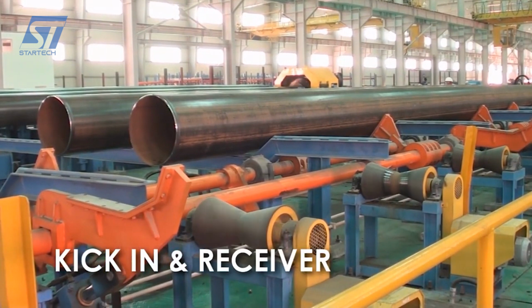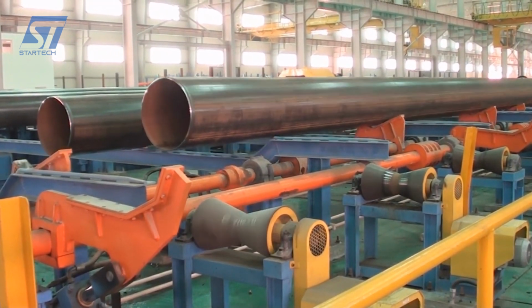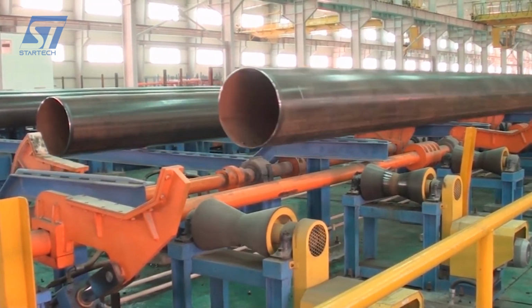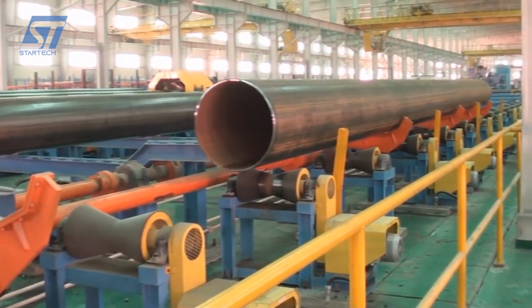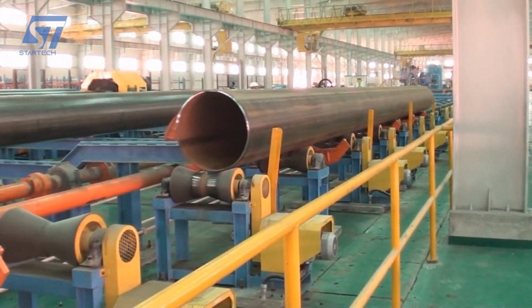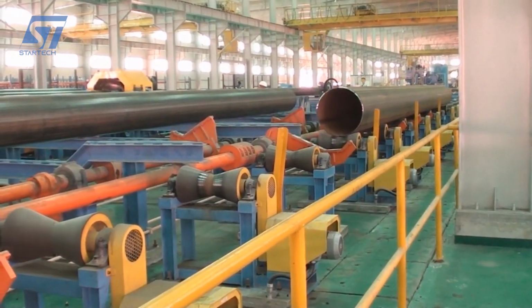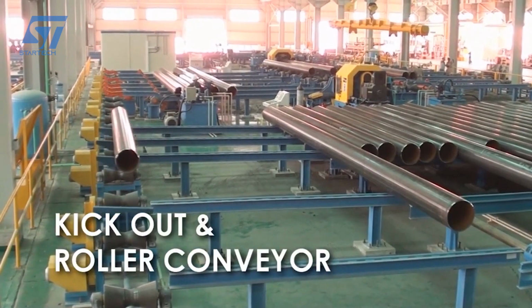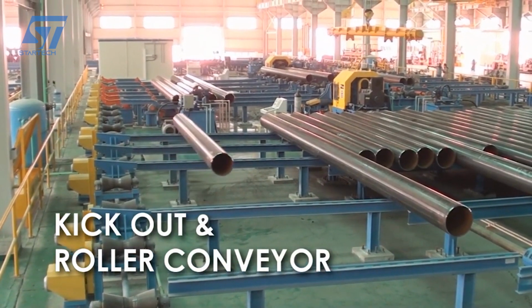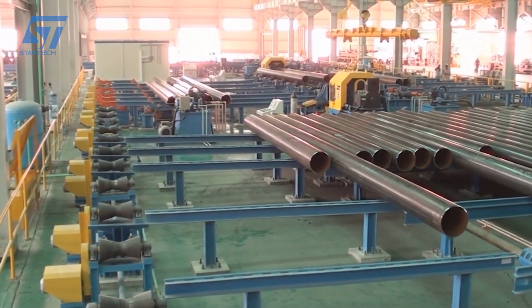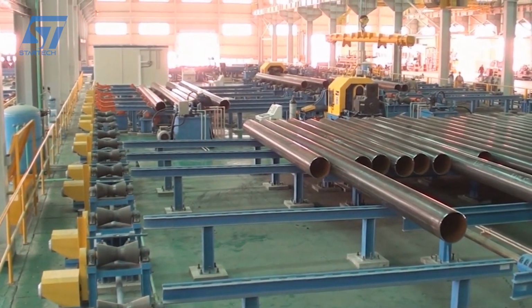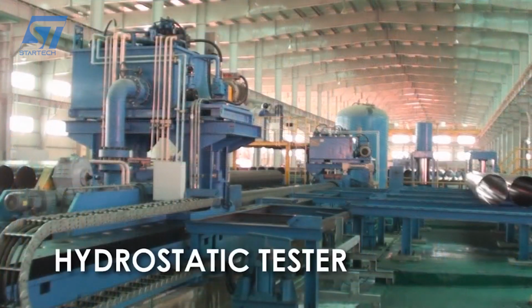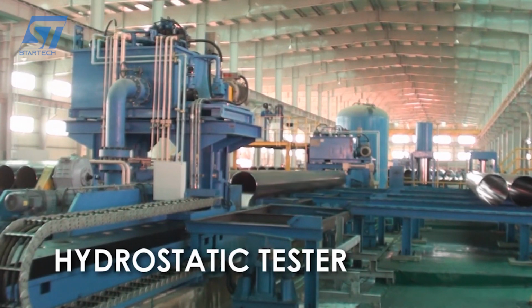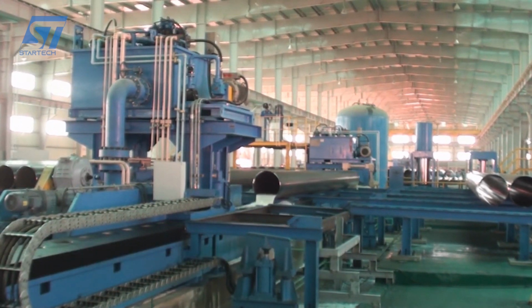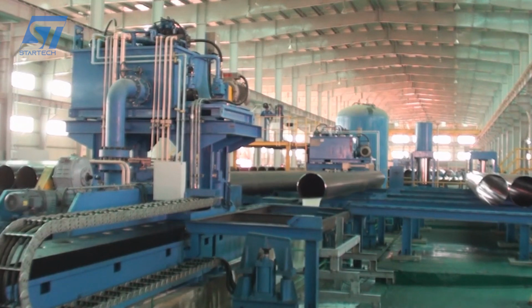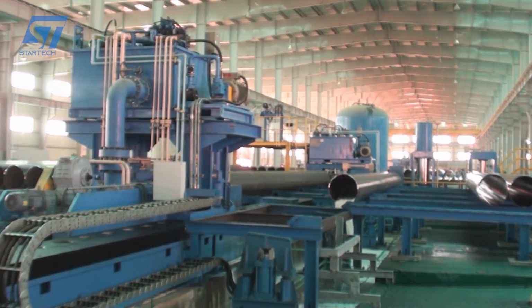The scrap rate decreased from 5% to only 1%, thanks to the ability to strictly control each stage, from forming to welding and cooling. The system allows quick conversion between different pipe configurations within just 15 minutes. Previously, it took up to 2 hours. Square, rectangular, and round pipes can be produced with sizes from 25 millimeters to 150 millimeters, meeting the diverse needs of customers. Dimensional accuracy reaches plus or minus 0.05 millimeters, far exceeding standard requirements. The weld seam is smooth, without defects, meeting international standards such as ASTM and ISO.